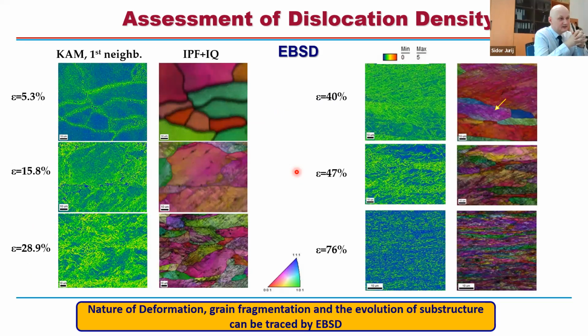Another important aspect is how those dislocations tend to evolve. So for this purpose, we did electron backscatter diffraction, EBSD, and then kernel average misorientation. And if you have inverse pole figures and you add IQ maps, you can basically see the substructure evolution inside materials. And for kernel average misorientation, if you take first or second neighbor, it does not really matter. You can clearly see where those dislocations tend to concentrate.